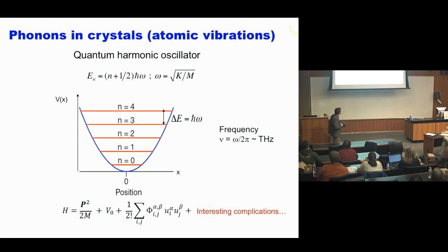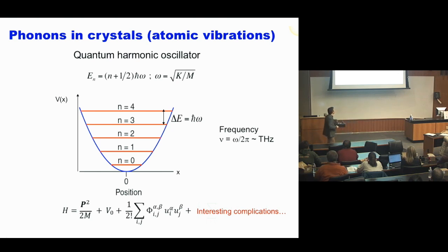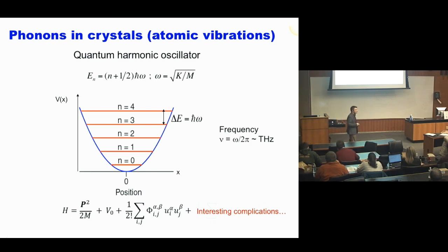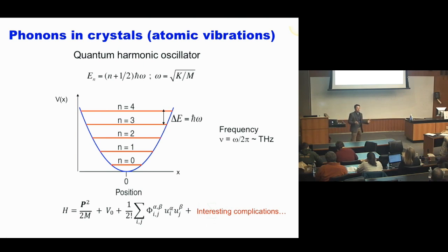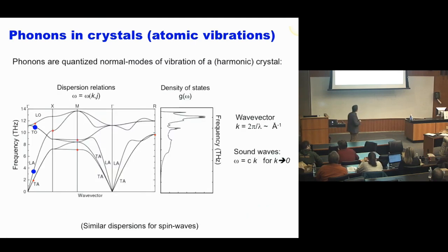If the oscillator is in the n=4 excited state, in phonon language we say we've got four phonons of this type occupied. The frequencies we're dealing with are quite high - atomic frequencies on the range of 10¹² Hz - because the masses are very light. They've been challenging to measure, but nowadays we have very powerful experimental techniques to resolve those vibrations in great detail, and we can also compute them from first-principles methods. In our group, we do both experiments and simulations.